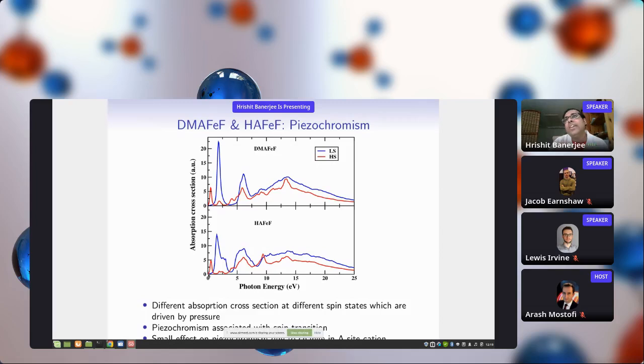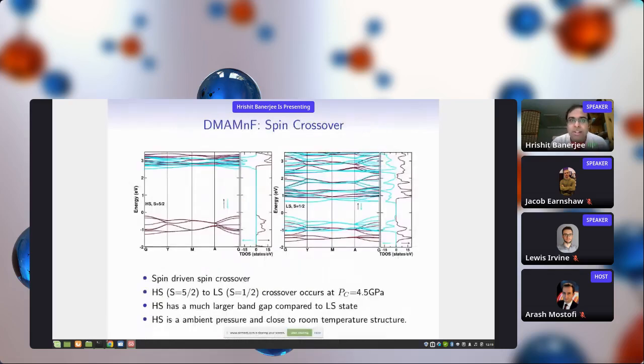However, their hysteresis widths are different, because you can tune the hysteresis widths by changing the A site cation and the hydrogen bonding, whereas, as I'll show in a minute, you can change the color change, or the piezochromism associated with spin crossover, by changing the transition metal ion. So for this, we also show a very similar mechanism of spin crossover in dimethyl ammonium manganese formate.